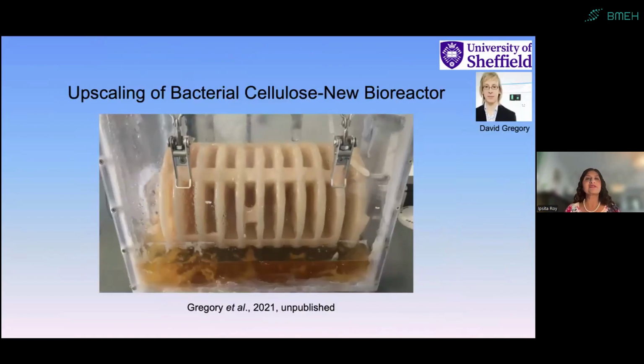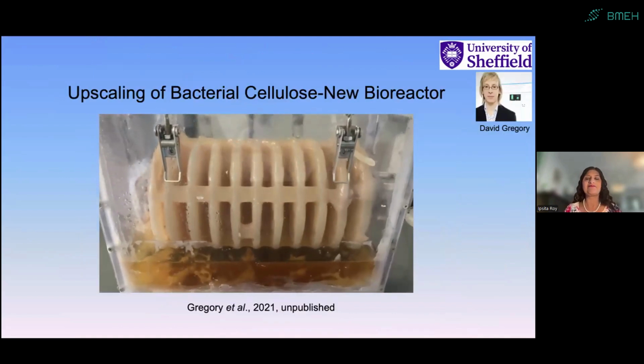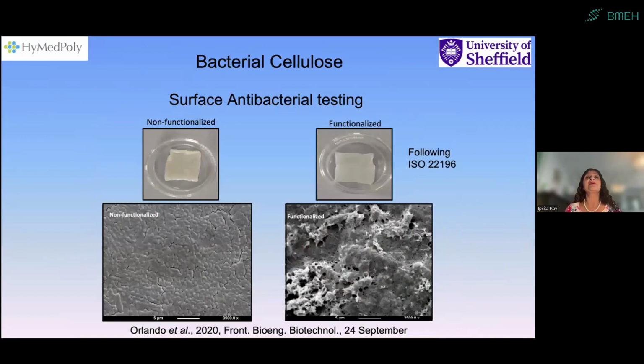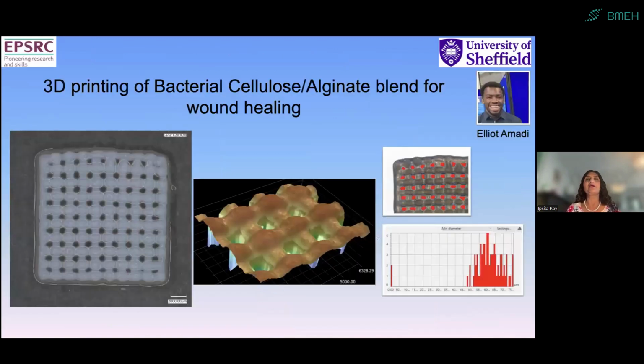We have tried to scale up this production and have produced antibacterial bacterial cellulose. As you can see here, the surface of non-functionalized bacterial cellulose has Staph aureus growing on it very happily, whereas when we functionalize them, as soon as they attach, they cannot grow and they lyse. We are also now making wound healing patches with this bacterial cellulose and alginate blend.